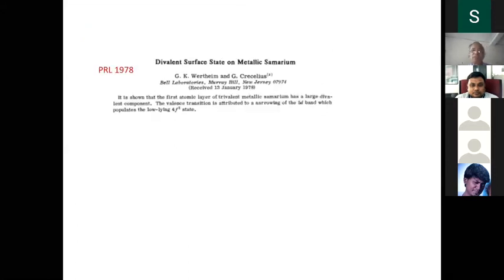And subsequently, even samarium metal, which is basically trivalent in the bulk of the material, with 6 electrons on the outer shell, shows something different at the surface. You look at the surface, and you will find that samarium is divalent. There's a surface valence transition.